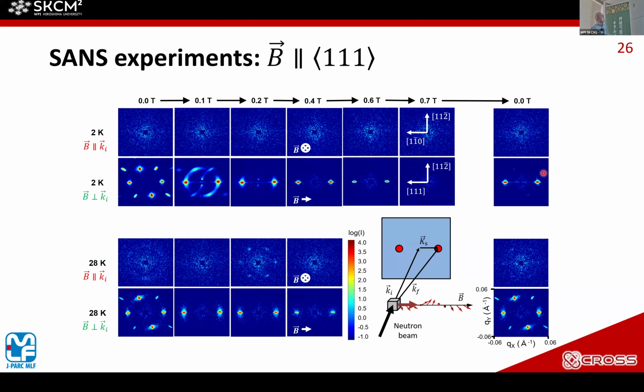So then, when we apply magnetic field along the 111 direction, the chiral axes merge into the 111 direction. So these peaks merge to this horizontal black spot, and after that we observe just one chiral axis like this. And from this result, we can say that even in the B phase region, we don't have any anomaly, just black spots due to the conical phase. And for 28 Kelvin, it's also observed, but when we apply field, it merges into one chiral axis, and it shows a similar case. So there is no difference between 2 Kelvin and 28 Kelvin.